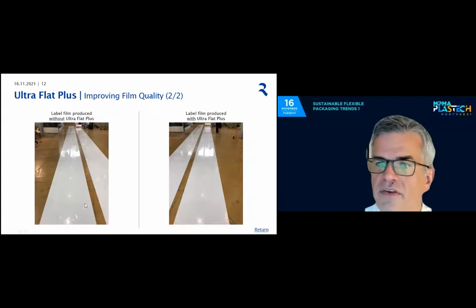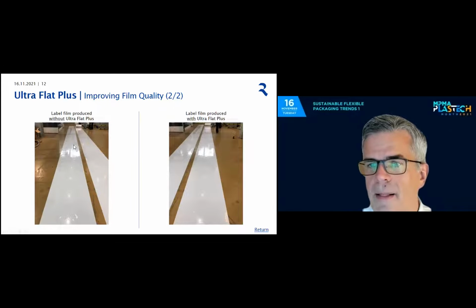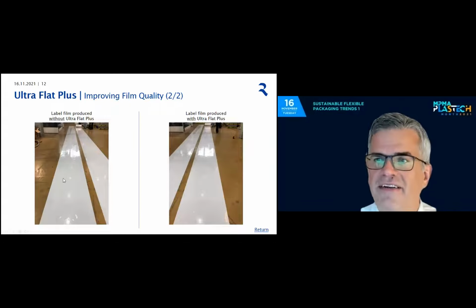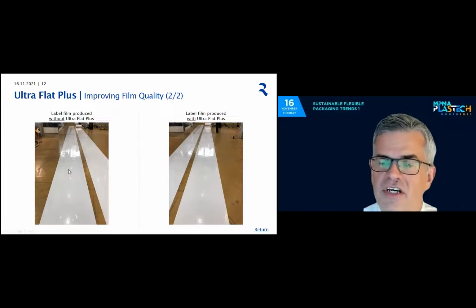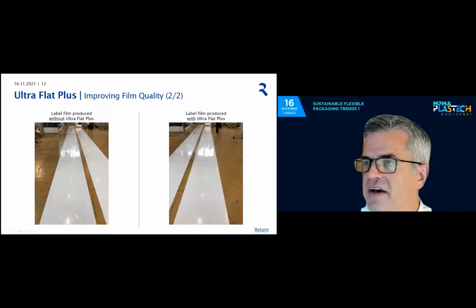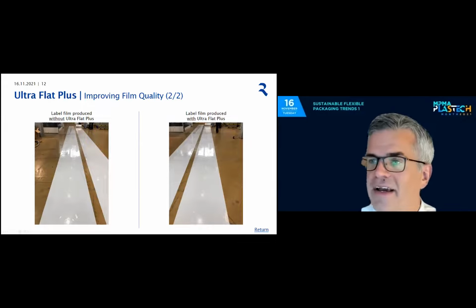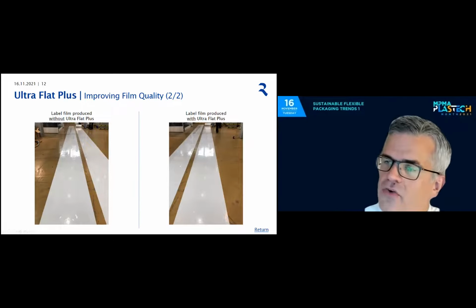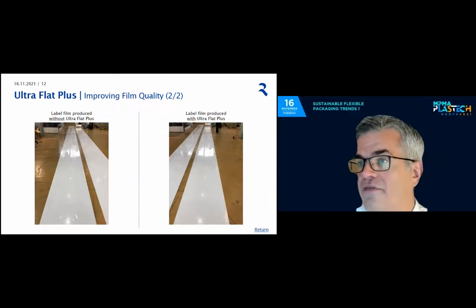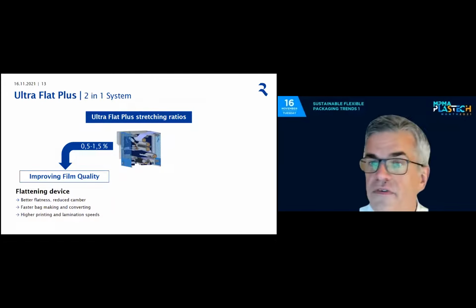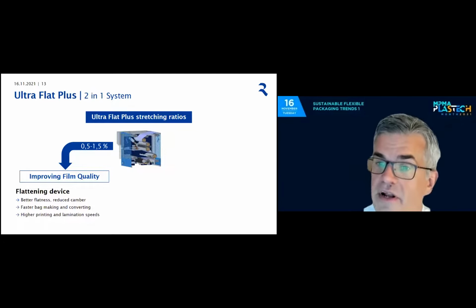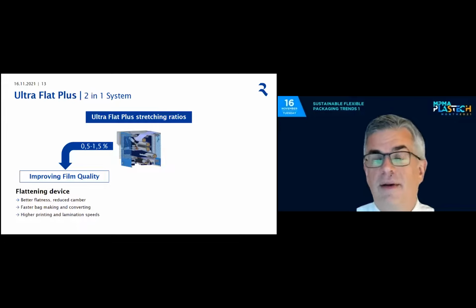The result of stretching only 1 or 1.5% is this one. On the left-hand side, you see a film without an ultra flat or flattening device, without being flattened by stretching 1.5%. On the right-hand side, you see the film with a function of an iron applied to improve flatness. So you can use this unit to stretch only a little bit to improve properties of lamination film.